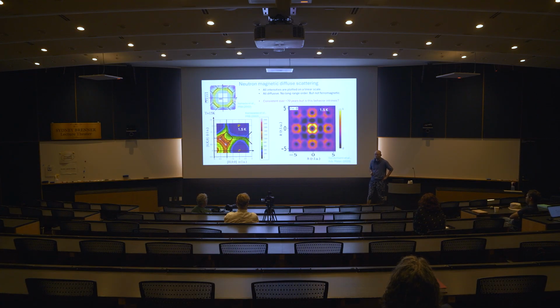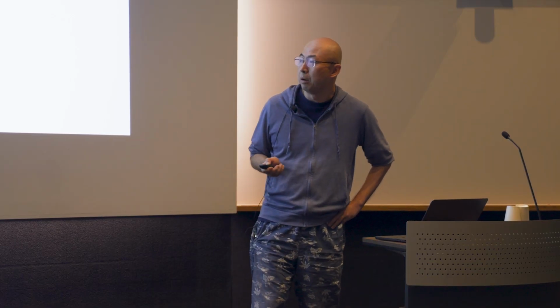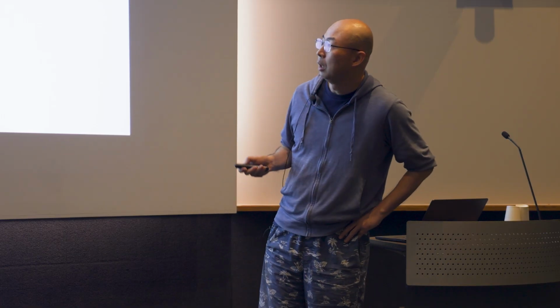But you ask the question, is this really the intrinsic behavior? So we came to the conclusion that we need to grow our crystals ourselves. That's the best part of OIST: I can start the lab with material development instead of doing the measurements I was used to doing. At that time, I had lots of consultation with my colleagues across the world, especially one at Oak Ridge. What I learned was that they developed a technique to use a flux to improve the sample homogeneity and quality. So I said, okay, I want to use flux too, but I want to use an even lower temperature.